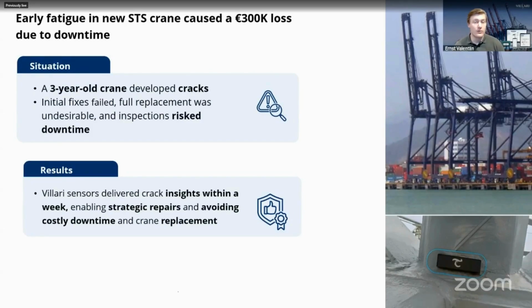within 3 years after it being in operation, it was already showing significant cracks and near failures of some structural members. To keep in mind, ship-to-shore cranes are typically designed to have about 25 to 30 operational years. 3 years was, of course, way too early, and in this case also still within warranty. So the first cracks that were found in this crane were repaired by the manufacturer under warranty.